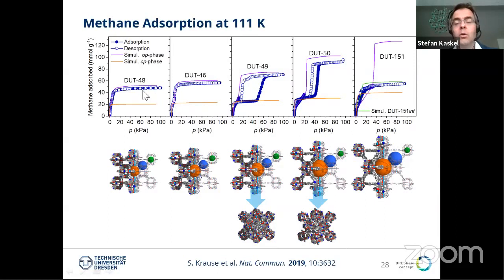And experimentally is what we find here, that there's a critical length needed to induce the buckling. So the shorter linkers 48 and 46, they don't lead to a buckling in methane adsorption at 111 Kelvin. Only starting from DUT 49, we realize the buckling and the NGA and the compression. And the new material that we published last year, DUT 50, also shows the NGA effect. Please also notice this is a huge experimental uptake here, more than 80 millimole per gram methane is a great capacity. And unfortunately, we were not able to make the DUT 151 as the open pore form because it forms an interpenetrated form. So here the behavior is more complicated.